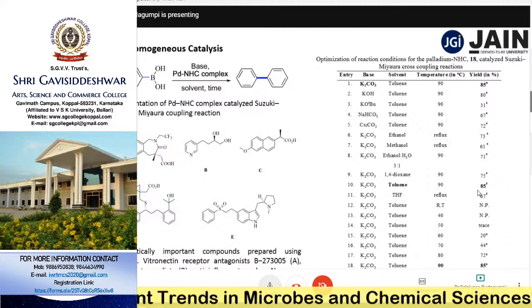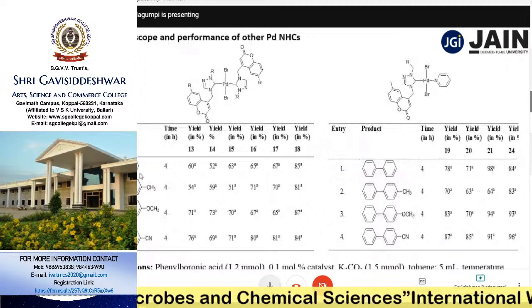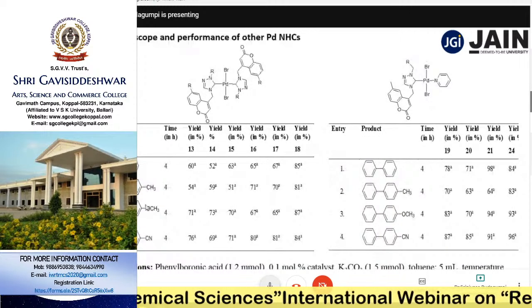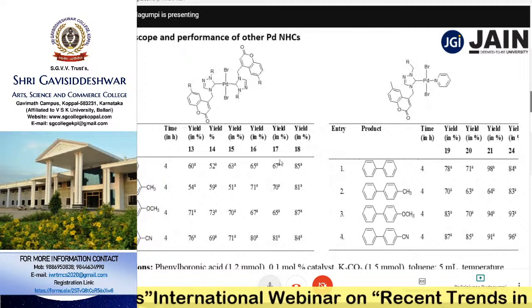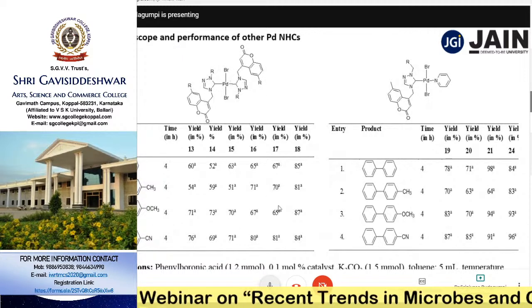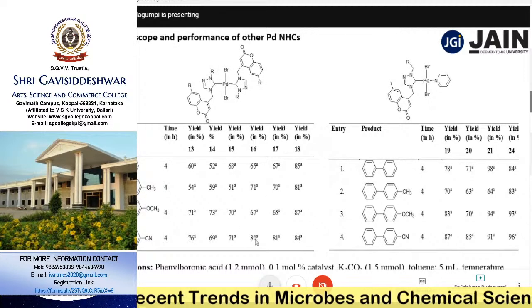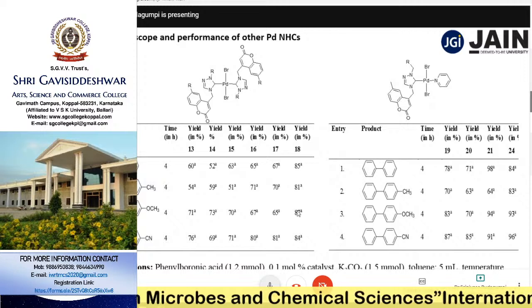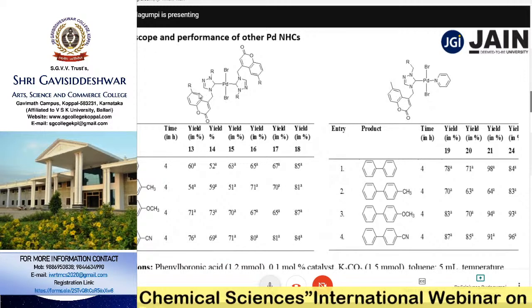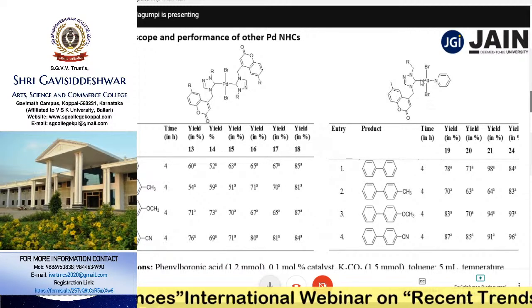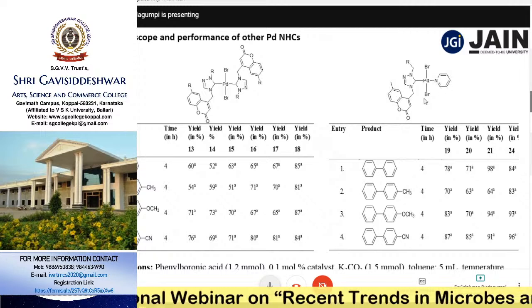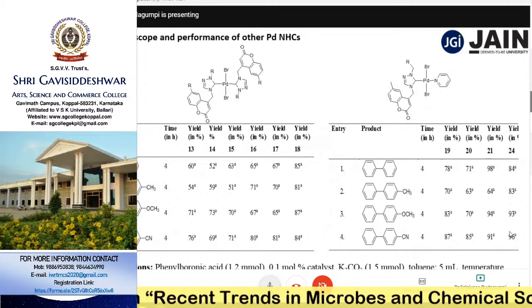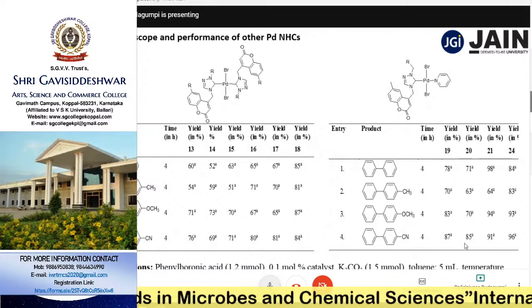So keeping this constant, we have studied the substrate scope. We have changed the substrates here, the coupling partners, with substituted coupling partners. Finally, we could get yields of up to 84%, 87% in a few cases with respect to the bis-NHC coordinated complexes, while the mono-NHC with the pyridine substitution gave somewhere around 96% yield.